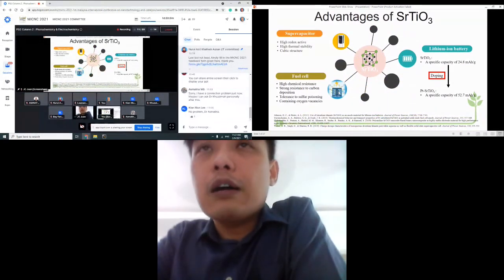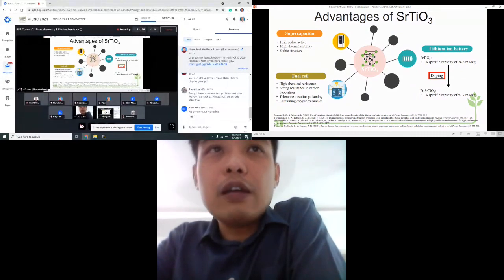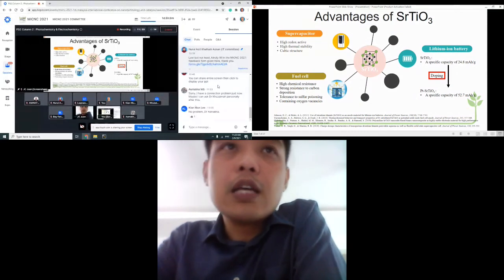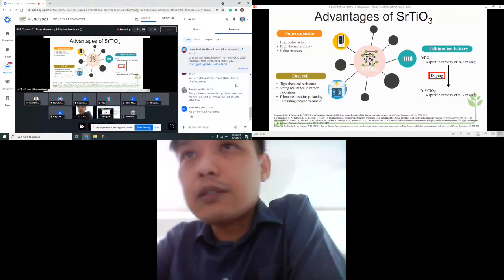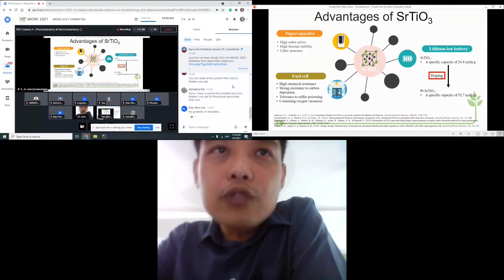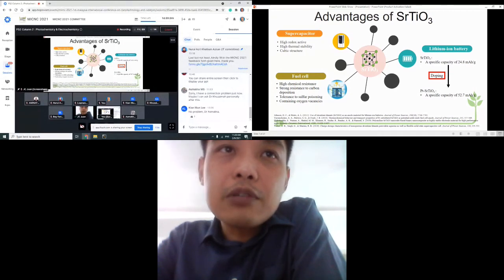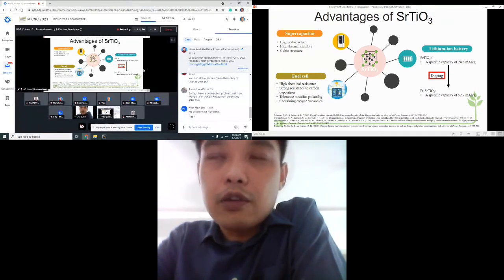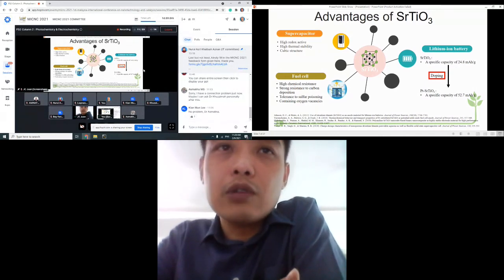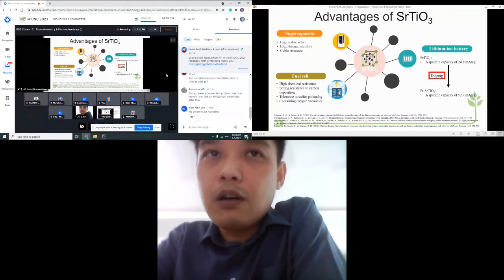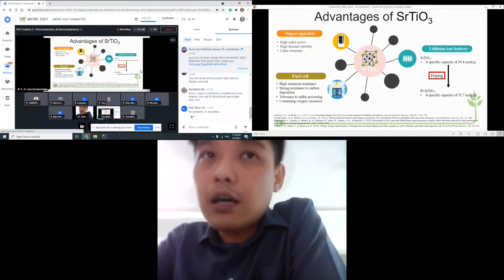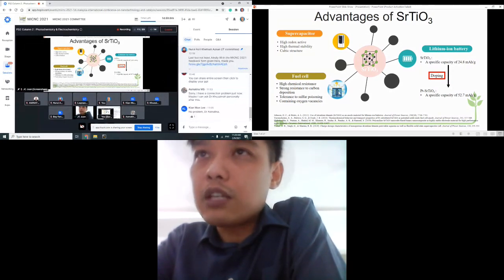Among all these perovskite materials, we choose strontium titanate, SrTiO3. We did some literature review and found that SrTiO3, one of the perovskite materials, has good potential because it has high redox activity, high thermal stability, and a cubic structure. It has also been used in fuel cells because of its high chemical resistance, strong resistance to carbon deposition, and tolerance to sulfur poisoning. Of course, in our battery, there is no such thing. But based on the literature, it shows good chemical stability and also contains some oxygen vacancies. Of course, the oxygen vacancy is not well studied. That's why we have this idea to introduce oxygen vacancies in the perovskite material.